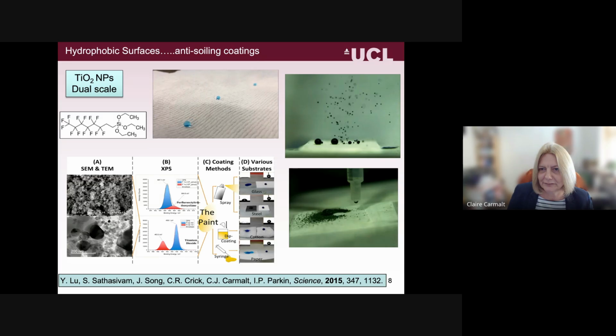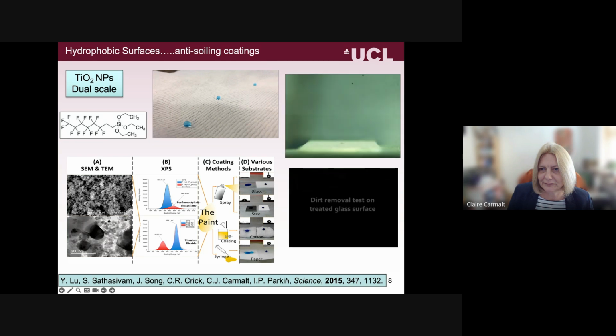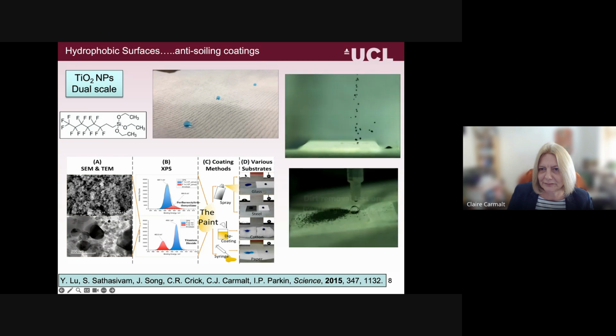Now, because it's like a paint, we're able to take different coating methods, and that's shown in the diagram shown here. So you can either spray them onto hard surfaces, such as glass and steel, or dip coat onto soft surfaces like cotton and paper. I'm just going to set these videos going while I talk. And you can see on the left side, that is the uncoated surface where the water droplet spreads out. On the right side is this coated substrate where the droplet is spherical and is repelled.